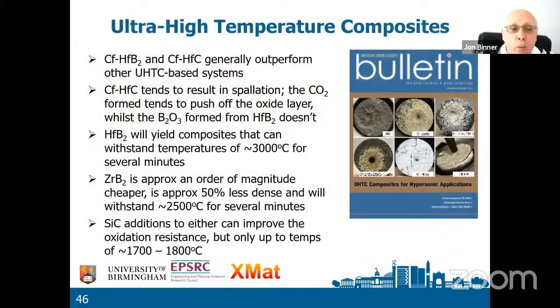So what do we know? We know that carbon fiber, hafnium diboride and hafnium carbide generally outperform other systems. There are more systems you can look at. We know the hafnium carbide isn't great. It results in the front face falling off, whereas the hafnium diboride is much better. We know the hafnium diboride based composites can withstand 3000 degrees centigrade for quite a few minutes.